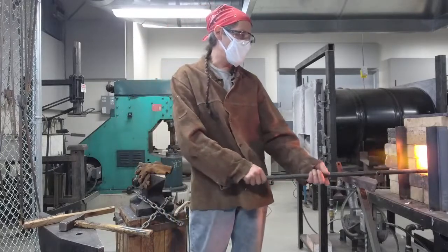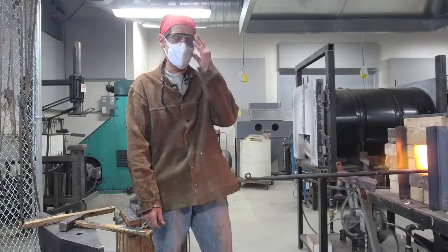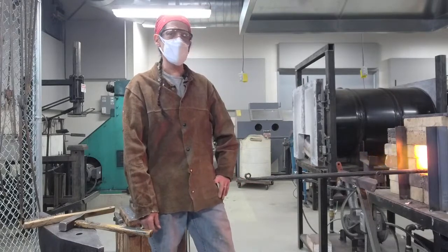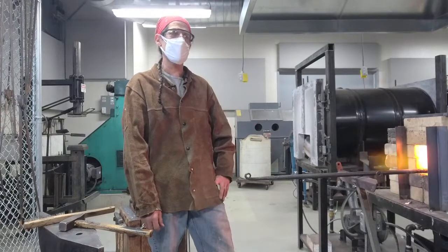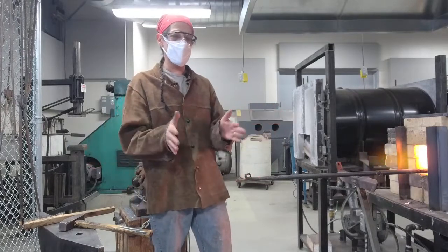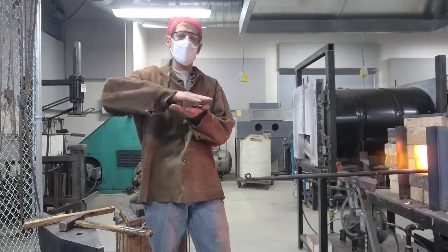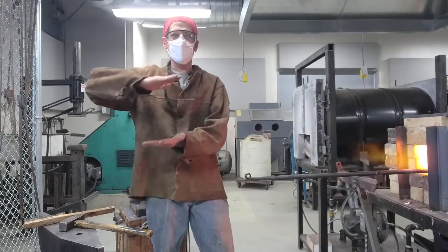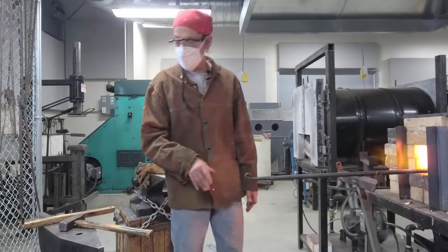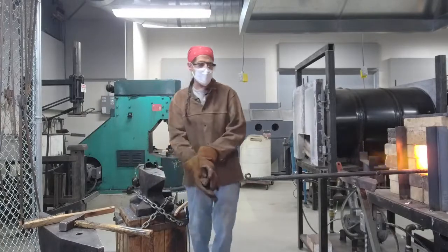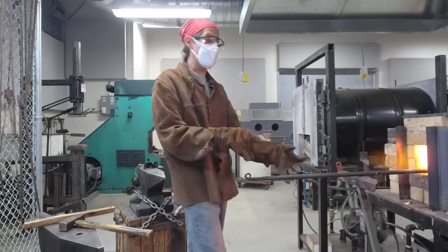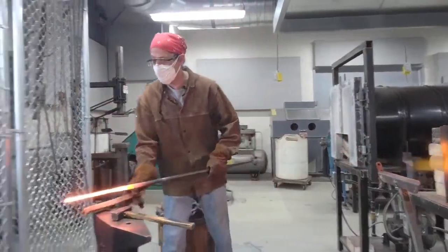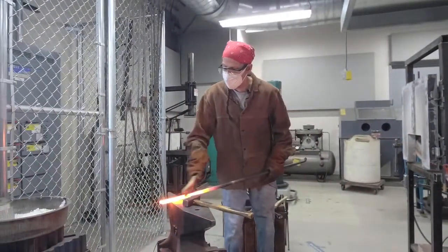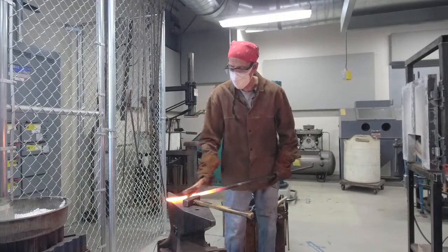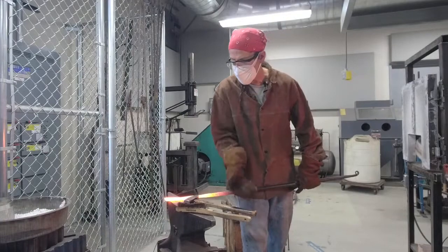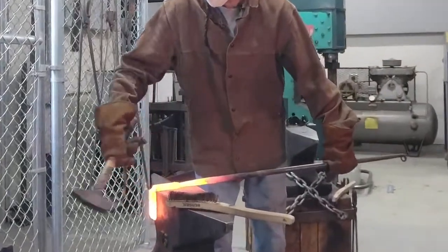So what's become quite popular, first time I saw it was in the early 90s, a lot of people are using hydraulic presses instead of a power hammer. They are not as loud. They take up a smaller footprint in a shop. So they use the press the same way, but they squish the steel together, basically. They compress it. By the way, the first few blows, whether you're using a power hammer or a press, you do very gently. I'm not flooring the pedal on the power hammer, for example. If I were to hit it too hard, the layers would slide. They would actually not stick. So I do it lightly at first, and then once I think it's gotten a good weld, then I can hit real hard.